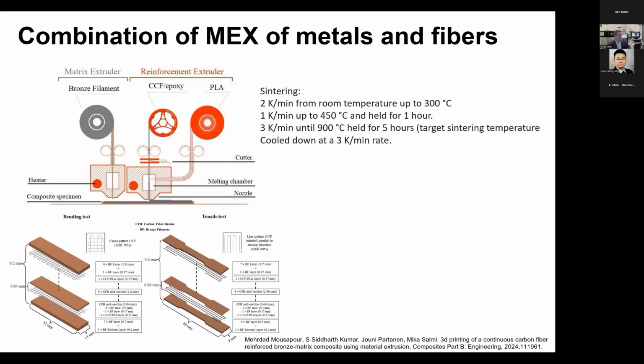But again, quite similar to the shape memory polymers. So we made test parts and put different kinds of fibers there. If you want to optimize some properties, for example for the bending test, we put this kind of cross pattern with an infill of 50%, and for the tensile test, we put a line pattern parallel to the tension direction with an infill of 80%. And again, we cannot put the fibers on top of each other layer. We need to make non-fiber layers there because they are slightly thicker than the normal layer, otherwise the printer doesn't work.